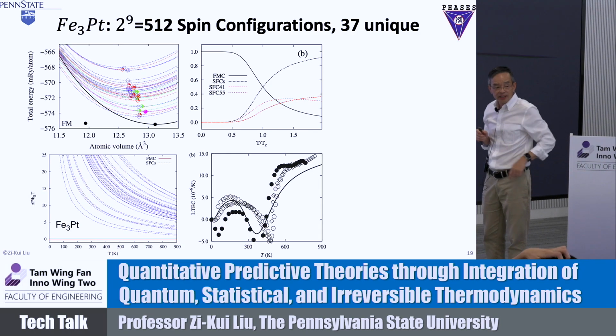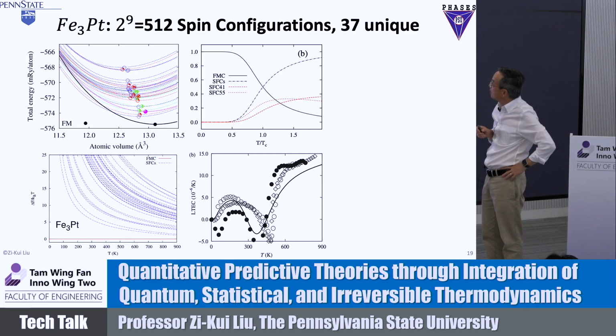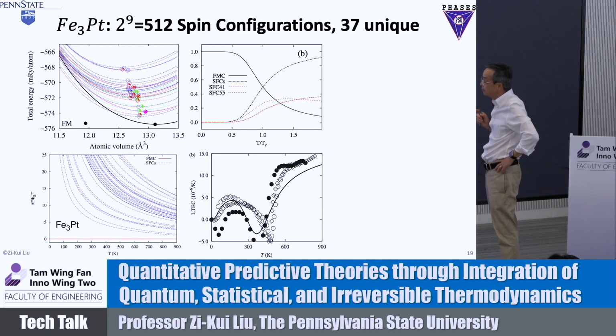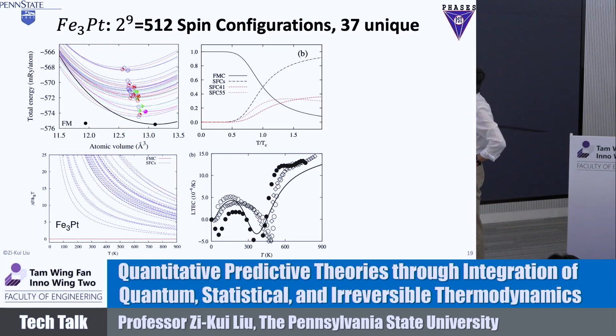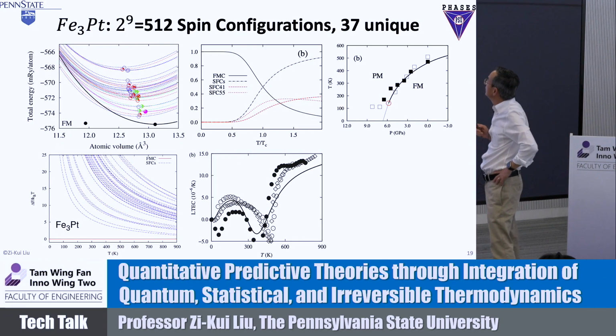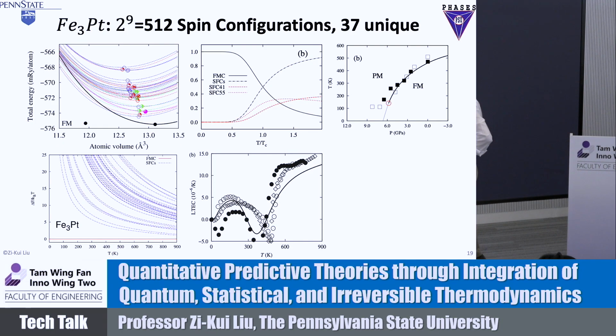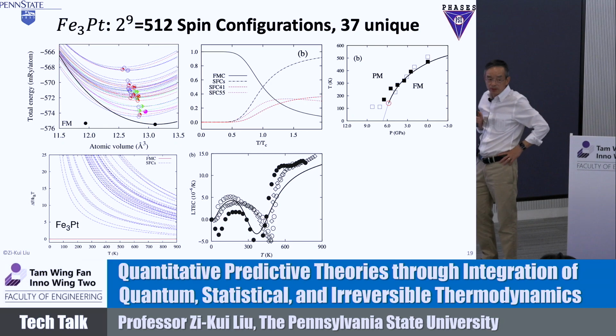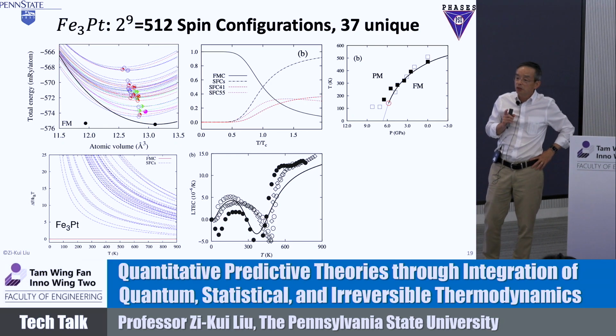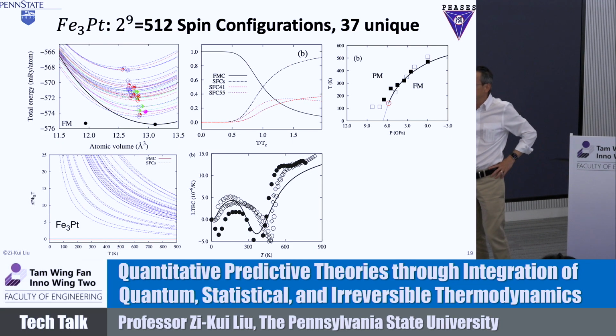We can calculate the negative thermal expansion at 0 pressure. You can see the symbols are from different experiments, the lines from prediction, from these 512 spin configurations, completely predicted from first principles, without any model, without any fitting parameters. And we calculate the phase diagram, the TP phase diagram. Again, symbols are from experiments and lines from prediction. No model, no fitting parameters.